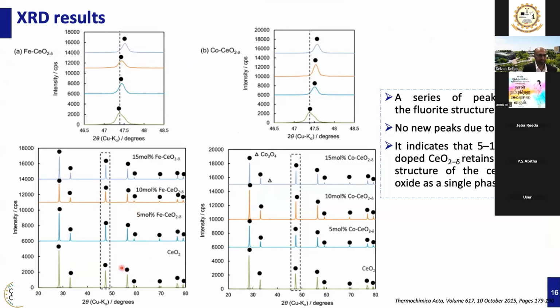Different colors represent a different amount of the metal doping. And as you can see, the series of peaks are due to the fluorite structure. And as you can notice, there are no new peaks due to doping. And it indicates that 5 to 15 mole percentage of iron doped cerium oxide retains the fluorite structure of the cerium-based oxide as a single phase.